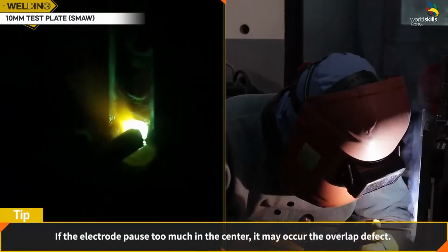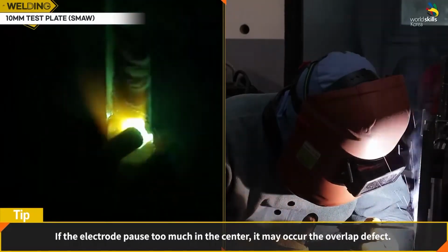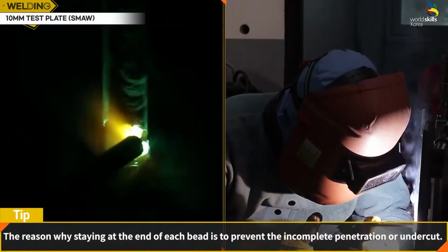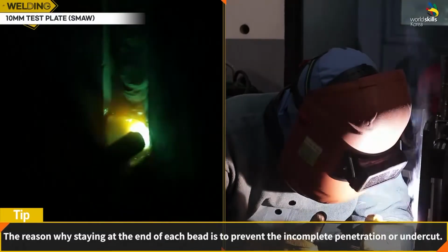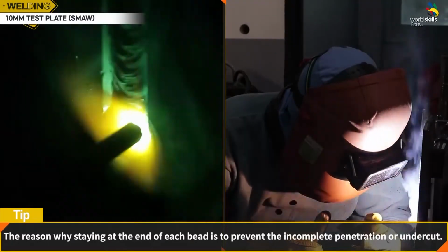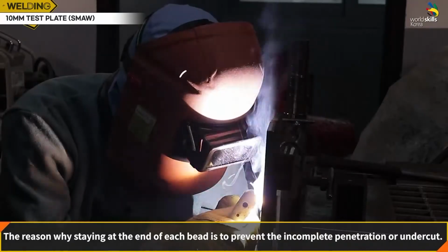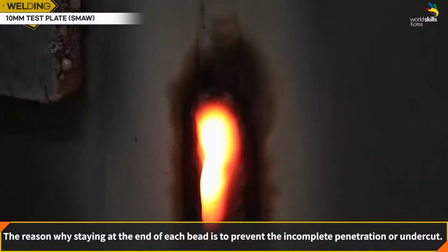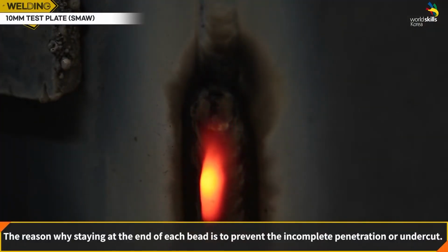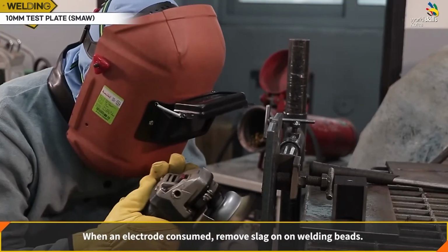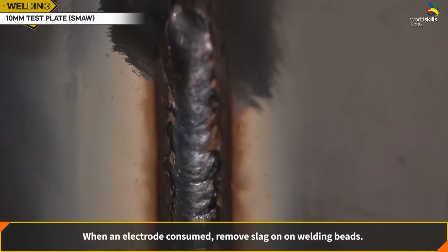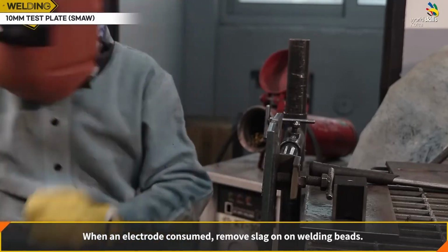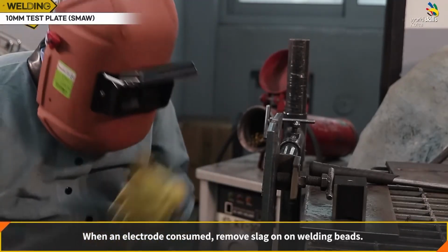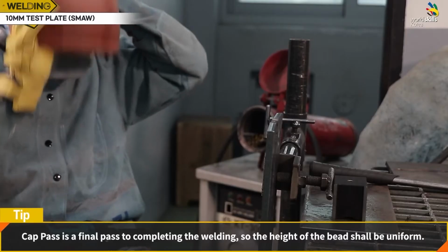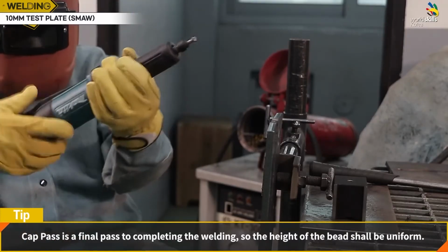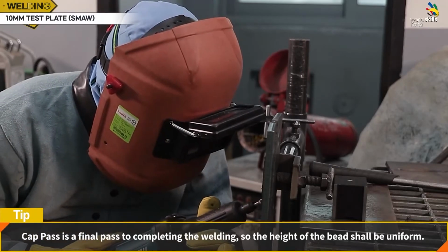If the electrode pauses too much in the center, an overlap defect may occur. The reason for staying at the end of each bead is to prevent incomplete penetration or undercut. When an electrode is consumed, remove slag on the welding beads. The cap pass is the final pass completing the welding, so the height of the bead shall be uniform.